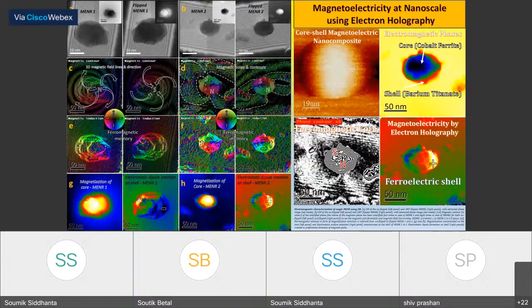But the other key thing, this measurement, which is also one of the toughest things, was to flip the grid which contains this nanostructure 180 degrees manually, and then again find the same nanostructure from thousands of the nanostructures on the grid and analyze it. The reason for this is that when we extract the phase from the flipped and the top surface analyzed nanostructure, the addition of this phase will give us the magnetic contribution. The subtraction of this phase will give us the electric contribution.